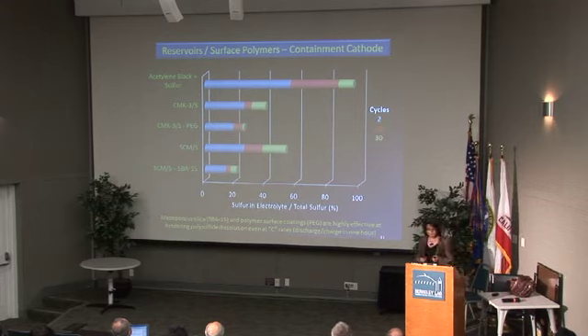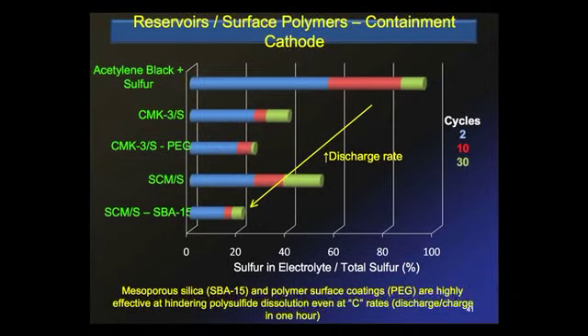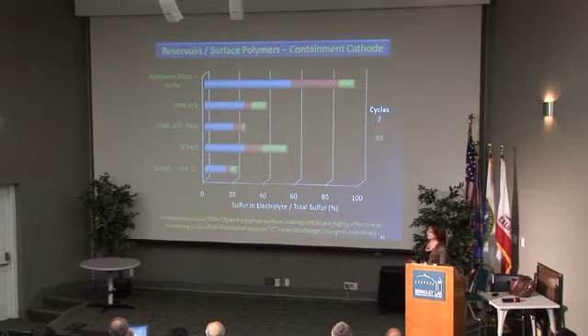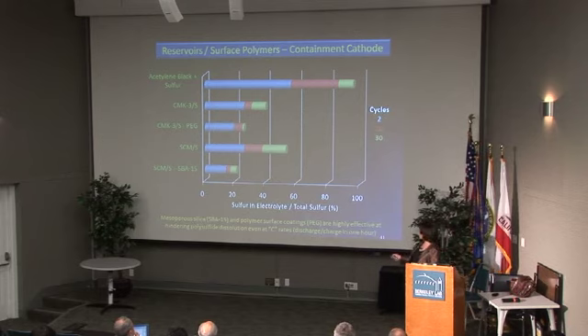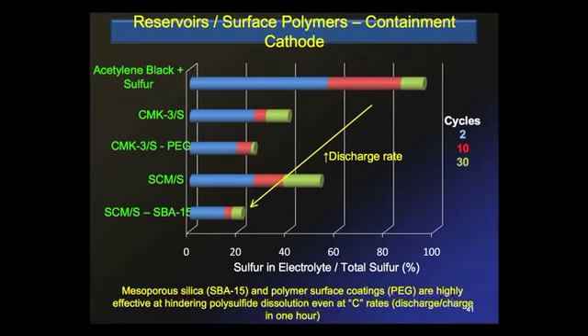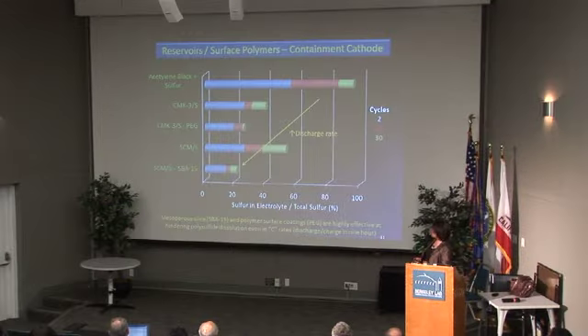So to summarize the sulfur part, this is data that shows the sulfur in the electrolyte. This is careful chemical analysis of the sulfur concentration. If you just mix up carbon and sulfur, within 30 cycles you have almost 90% dissolved in solution. The CMK3 manages to hold on to most of its polysulfides for a reasonable number of cycles. We were getting about 40% dissolution, but if we modified with the polyethylene glycol, we're down to just above 20%. If we go to a larger pore system, we now have a fair amount of dissolution, whereas if we incorporate these polysulfide reservoirs, we again diminish the polysulfide in solution down to about 20%. So we've gone from a system with lower discharge rates and unacceptable dissolution to fast discharge rates at about a C rate with only 20% dissolution.